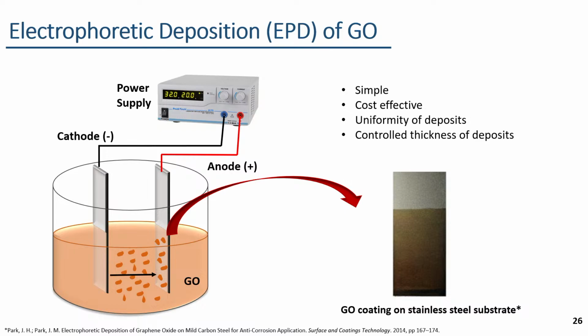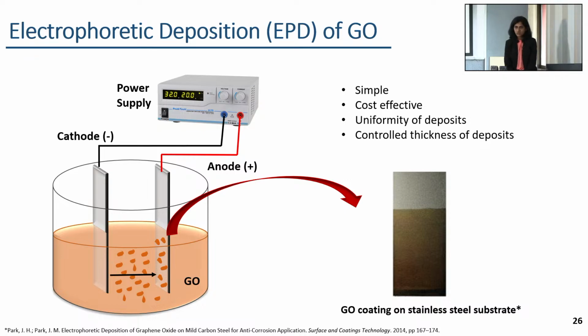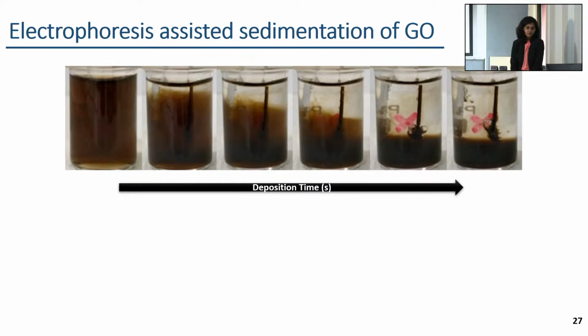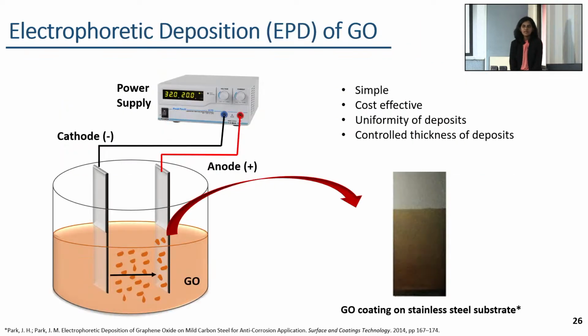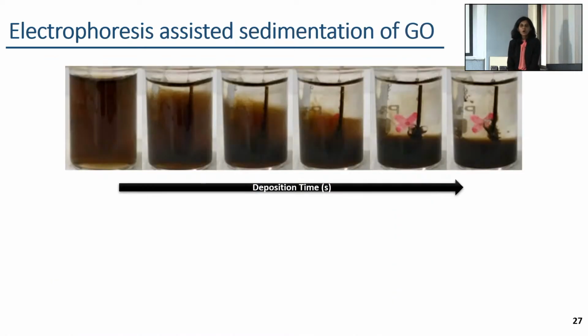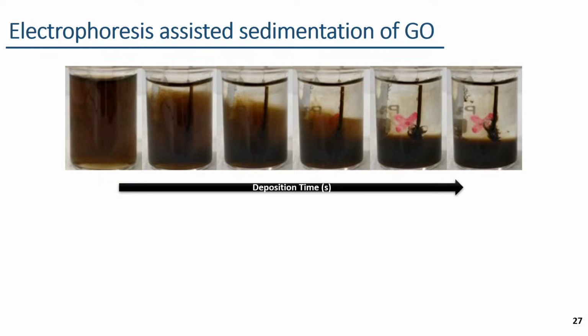So, in this study, the electrophoretic deposition of graphene oxide was carried out using a glass beaker setup under different EPD potentials. During this EPD process, the negatively charged GO particles move towards the positively charged anode under the effect of the electric field and get deposited on the anode. During the same EPD process, we can observe the separation of the GO solution into a clear supernatant and a sediment over the deposition times, as shown in this image.